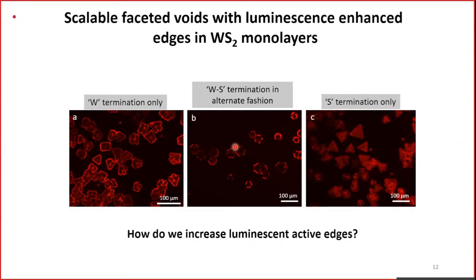What is interesting is when we have this kind of sulfur and tungsten termination alternatively, we can clearly see a particular edge, right? This is a fluorescence microscope image. It is actually more active. The emission is not uniform in all the edges. Enhancement at the edges is known, but only a particular edge is actually more active for the emission compared to the adjacent edge, right? We are trying to see in the literature why it is happening and so on.